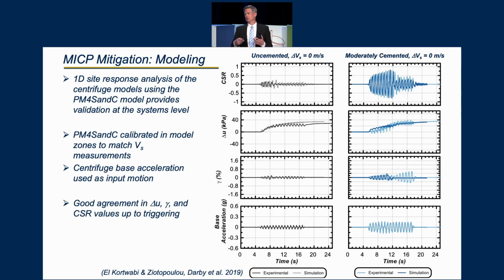We also have been able to do some 1D modeling with PM4SandC in order to simulate this same response. And in this case, the shear wave velocities measured in the centrifuge were used to calibrate the numerical model. And on top of that, the input base motion from the centrifuge test was the input base motion for the numerical model. And so results are shown here on the left for the uncemented case, with the experimental results being in the dark line. And on the right-hand side, it's actually inverted. The experimental results are in the lighter line. But in both cases, we can see that particularly up to liquefaction triggering, we can get pretty good agreement with respect to the centrifuge data as well as the numerical simulations and the combination of those.